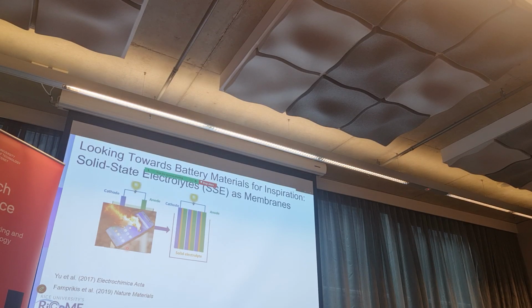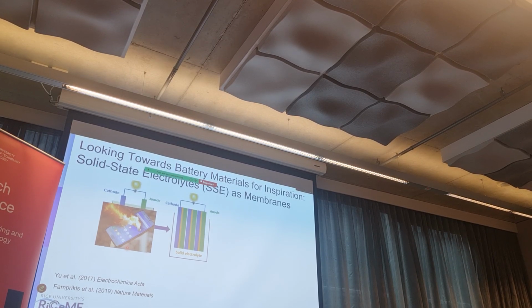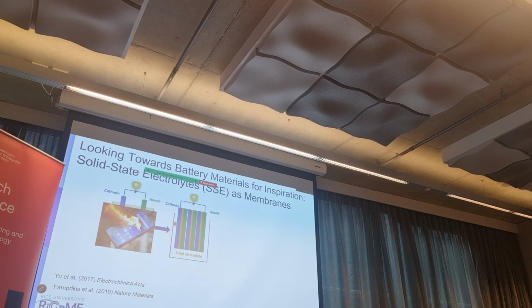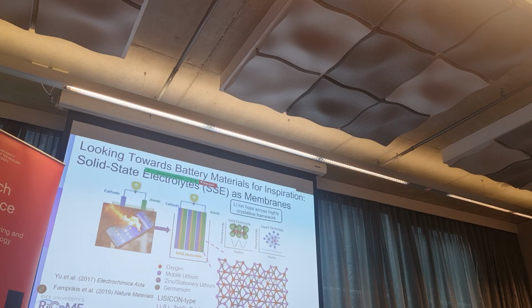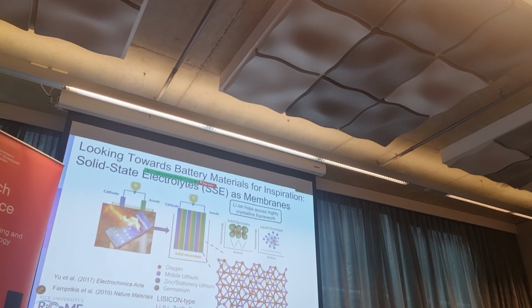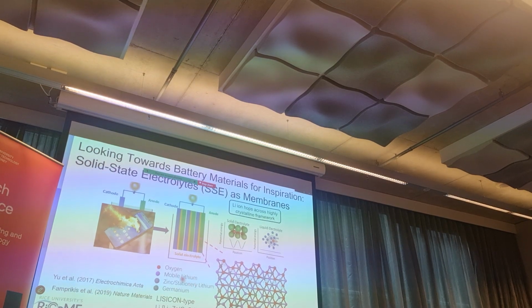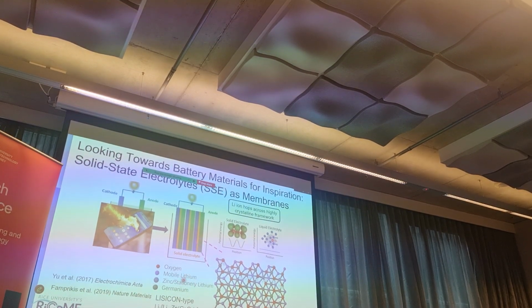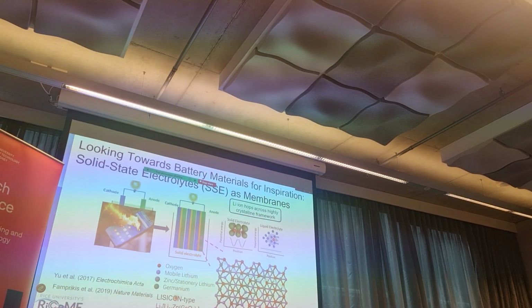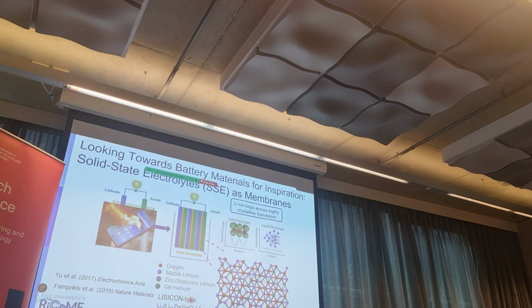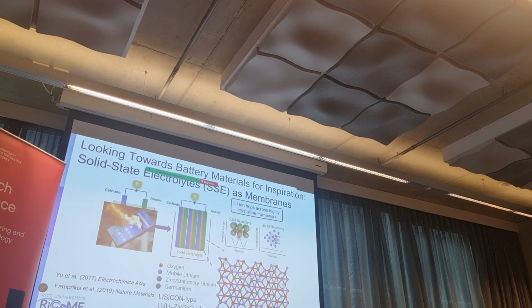So a lot of research moved the battery industry toward solid state electrolytes. Instead of liquid electrolyte, we use solid state inorganic electrolyte in which lithium can move. It's a very complex structure, a polyhedra, very well connected crystalline structure which includes many metals, and you can dope them with germanium and so on, giving a very complex transport mechanism.